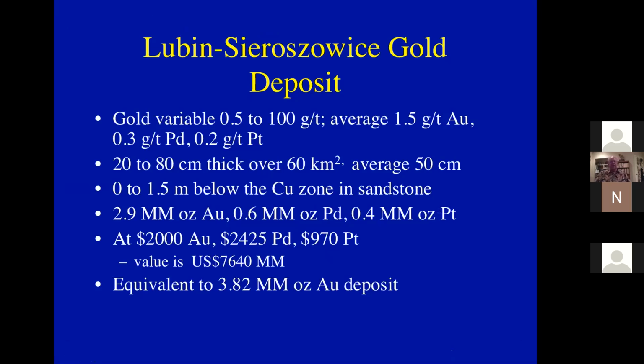So in this district, gold is variable from half a gram per ton to 100 grams per ton. It averages 1.5 grams per ton gold, 0.3 grams palladium, 0.2 grams platinum. It's a thin zone that's not specifically identifiable except by assay, that is 20 to 80 centimeters thick, averages 50 centimeters in thickness, and it occurs over an area of 60 square kilometers.